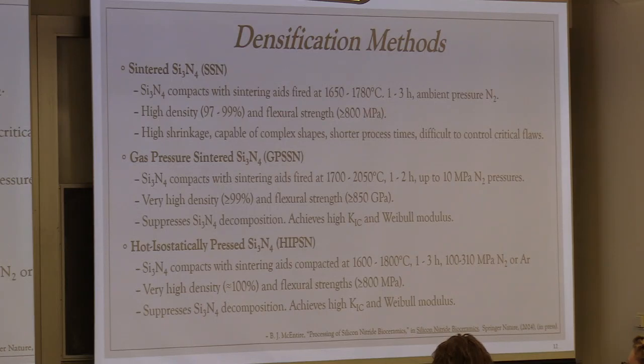But the problem with it is that the process defects kind of started to show their head in this, and you got basically materials with fairly low Weibull modulus, or reliability in this case. So the takeoff from that is they started applying pressure to the sintering process. And so there was a process developed called gas pressure sintered silicon nitride. And this is where they would apply a certain amount of pressure during the densification process. This would contain and prevent decomposition of the silicon nitride during the process.